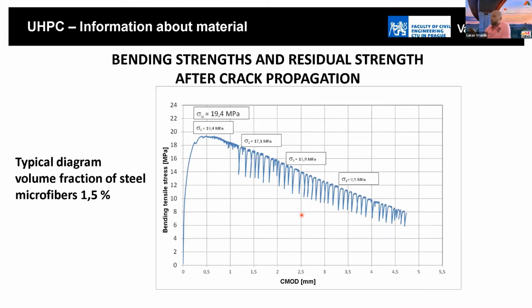And if we take into account this behavior, it is possible to design very thin elements. We could increase the slenderness of the element, and also we could reduce the dimensions of the members. So it is very good for the designing. And also if we take into account the effect of the increasing compressive strength and also the effect of the flexure tensile strength, we could really optimize the design of the cross sections. If we compare it, for example, with steel, it is very similar, also the dimensions and also the shapes of these members.